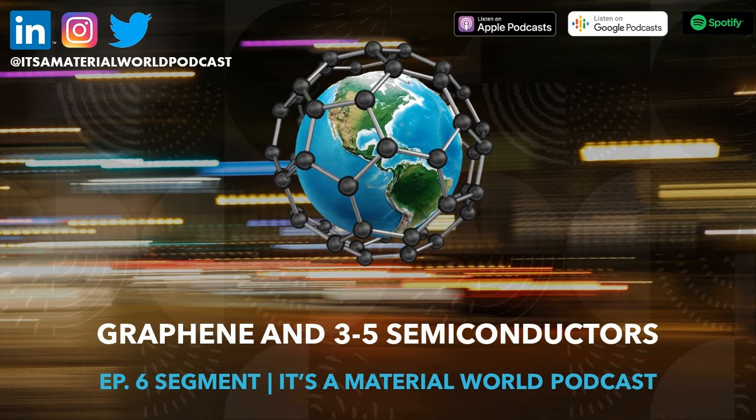And that's why the 3-5 semiconductors we talked about are coming up. Gallium nitride has been a very nice alternative, especially for power electronics. Why? Because gallium nitride performs better as compared to silicon at higher voltages and at higher temperatures. It has much faster frequency speeds and switches faster. So all of these things that I talked about, which are temperature, voltage, and frequency, what do they all drive into? Finally, your systems to be more compact, faster, with lower switching losses, higher frequency, and higher efficiency. All of these are better. So gallium nitride, or 3-5 semiconductors for that matter, is gaining interest.